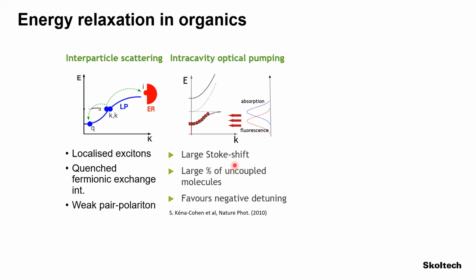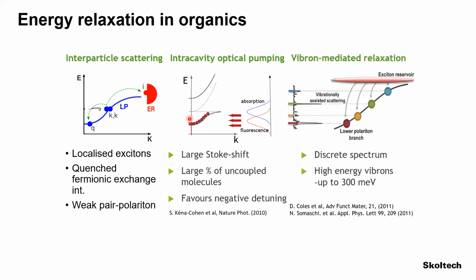There is another method that we actually studied now more than 10 years ago, and we transferred to organic semiconductors from some first studies that we did in my group on inorganic structures. That is really relying on the so-called vibron-mediated relaxation. Those who have been working with inorganic semiconductors know that we have vibrational modes, the so-called phonons, with which, if you use, for example, an LO phonon, you can lose a lot of energy with one particle emission. So we studied back in 2011 how you can actually use, instead of phonons, vibrational modes of the molecules to release a lot of energy in one particle. And this is actually what we found to be a very, very efficient process. With one scattering event, emission of one vibron, you can lose up to 300 meV, which is a very large amount of energy for this kind of semiconductors.